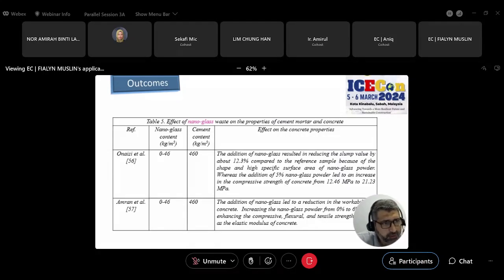So Onaizi et al. used up to 46 kilograms per cubic meter of nanoglass content with cement content of 460 kilograms per cubic meter. They observed that the addition of nanoglass resulted in reducing the slump value by about 12% compared to the reference sample because of the shape and high specific surface area of nanoglass powder. Whereas the addition of 3% nanoglass powder led to an increase in the compressive strength of concrete from 12 megapascals to 21, almost 80%. Amran also used the same percentage, but he observed that the addition of nanoglass led to a reduction in the workability of concrete. Increasing the nanoglass powder from 0 to 6% enhanced the compressive, flexural, and tensile strength of the concrete mix.